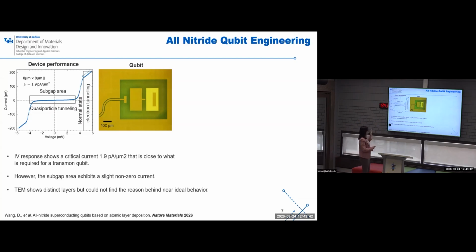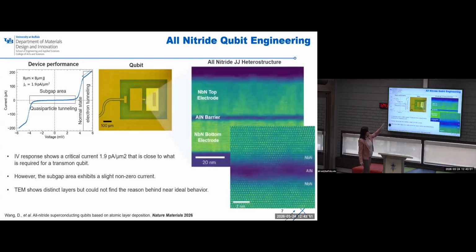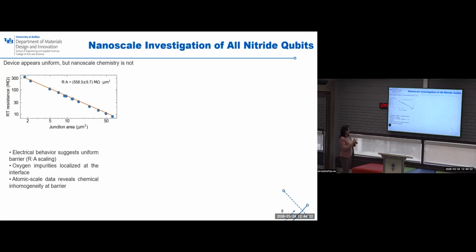okay? Now, the first thing, we start with the device. We grow the device, we saw the device working well, but not in the ideal condition. So then we have done the TEM study, and in the TEM study, first we want to see if the structure was all good, because we know that all the device problems come from the material structure. When we look at the TEM, this looks pretty good. We don't see much problem. There is a good top electrode, bottom electrode. The barrier looks not diffuse, because we have worked on other qubit systems where we see a diffuse barrier and a lot of other issues with chemical segregation. We don't see that.